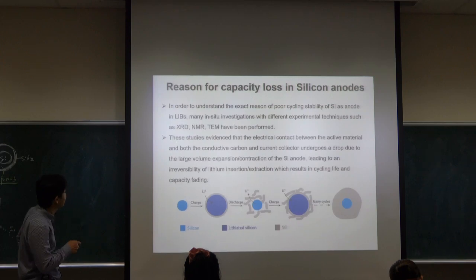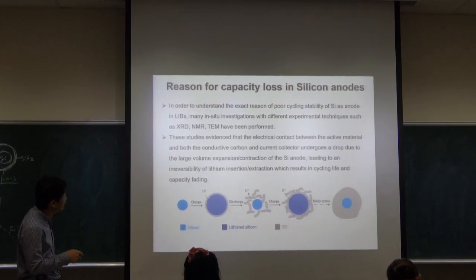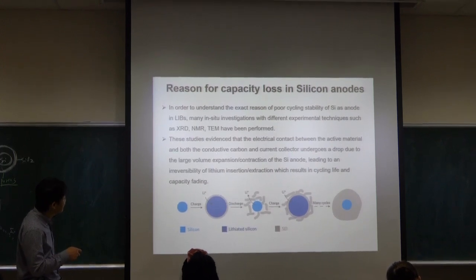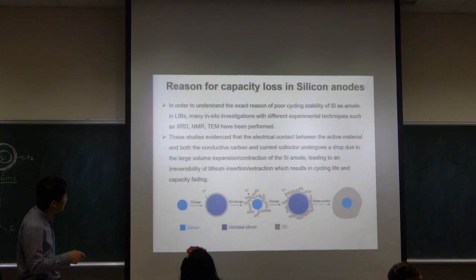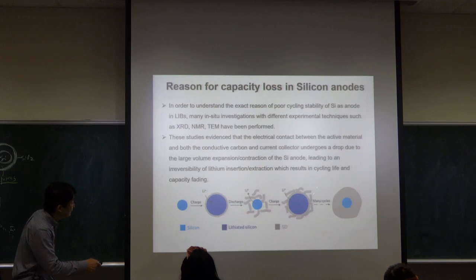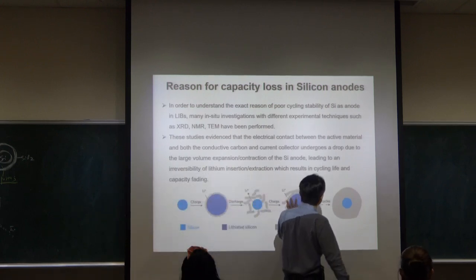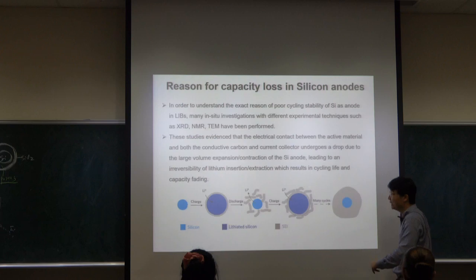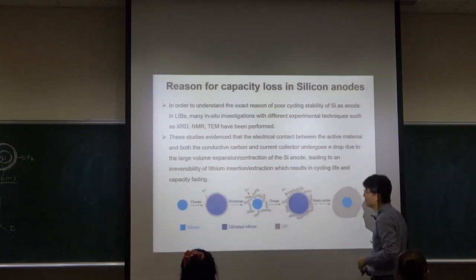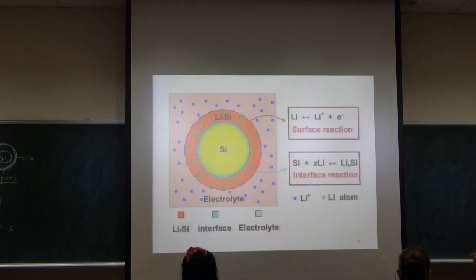So let's look at the bottom side. This study shows that the electrical contact between the active material and both the conductive carbon and the current collector undergoes a drop due to large volume expansion and contraction of the silicon anode. So this will lead to irreversibility. This is the cause of the cycling lifetime fading. Fading doesn't mean failure, okay, but capacity fade, because of the thicker SEI after many cycles. That's because the electrolyte will always react with the surface of the silicon.